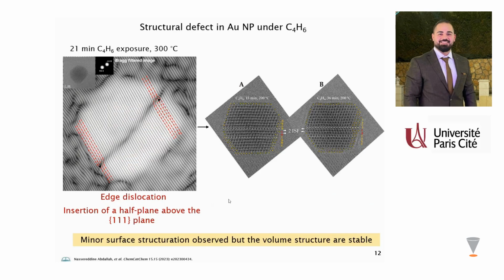To identify the structural defects, we applied a Bragg filter on the FFT of the image of the nanoparticle obtained at 300 degrees Celsius. As you see here, we identified two edge dislocations in two different regions of the particle due to the insertion of a half plane above the 111 plane. Of course, this edge dislocation evolved into two intersecting stacking faults. After 15 minutes of monitoring at 200 degrees Celsius, and after 63 minutes, we saw that the stacking faults are still there.